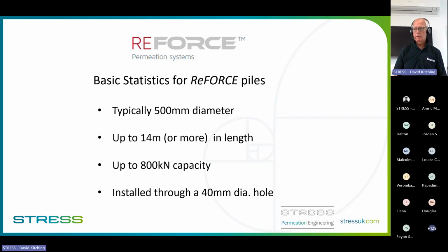A 3.5 meter deep lance ReFORCE pile was created and then tested to, well, basically as far as we could take it. We used a 35-ton excavator, and we were starting to tip it back. The maximum we got to was just under 21 tons, and we didn't want to go further. There was no way of doing the test any higher than that, but we know it would have taken hugely more capacity than that, because we got nearly no deflection at all.